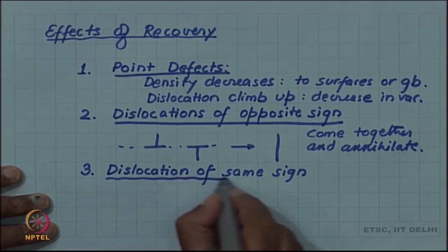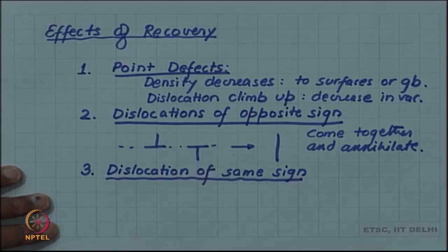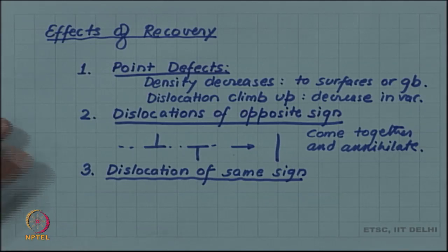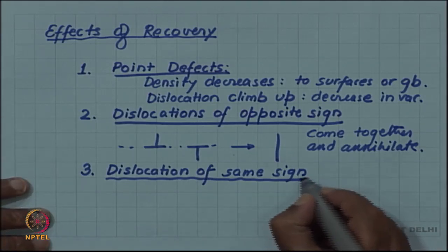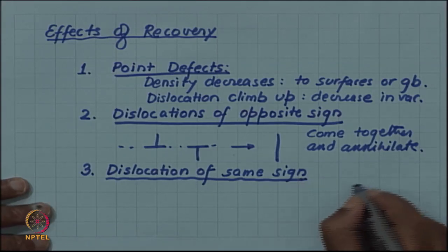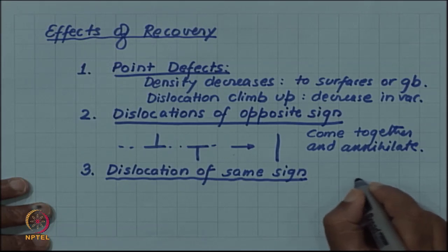Dislocations of same sign - if there is excess dislocation then this annihilation may not cancel all of them. Excess dislocations of the same sign will be left and these dislocations try to align themselves one above the other to reduce their strain energy.